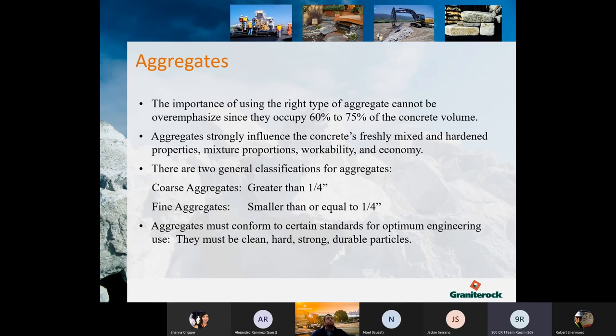So we have a couple different operations. In certain areas, it is settled so that the solids are out of the slurry, so that it is cleaner water. And two, in some locations, we do introduce admixtures to neutralize any effects that leftover particles would have on new concrete. And we do test that regularly. We have a monthly test just to make sure that we are not affecting the concrete in any negative way.